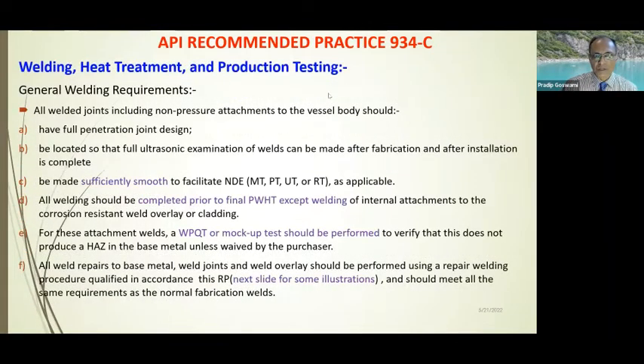And general welding requirements, basically all welds, including non-pressure attachments, should be full penetration type. There should not be any consideration of partial penetration joint design in these equipments at all. And they should be welded in such a fashion, or the location would be such that full ultrasonic testing of the welds can be done after fabrication, after the installation is complete. And definitely they should be sufficiently smooth, ground smooth, to facilitate this kind of NDE, that is MPI, PT, UT,